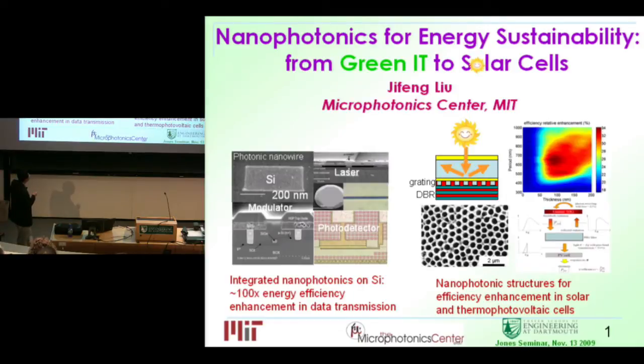And the other side is about the solar cells. So we know that solar cells are a really good renewable energy harvesting apparatus. However, we need to reduce the cost to make it more feasible and competitive with fossil fuels. So here, instead of using a bulk silicon wafer as people used to do with solar cells, we're now using a very thin layer of silicon. The benefit there is that you really throw away that material cost, which is half of the solar cell module cost for now, and also you reduce the cost of processing, because this thin film deposition is a relatively low temperature process, about 300 degrees, while for bulk silicon you have to go to 1,000 degrees to get the material. So it can potentially give you a significant reduction in the cost.